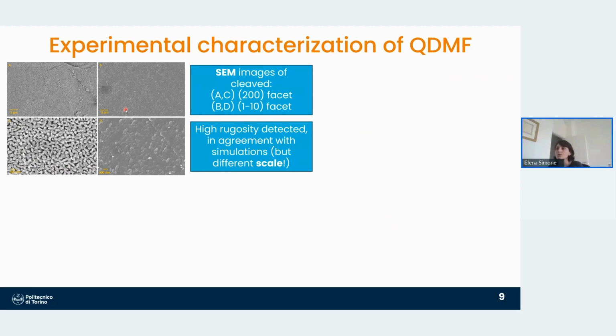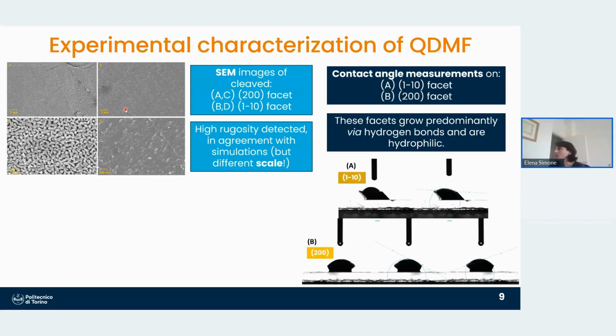So we have to consider that the scales are different between the simulation and the SEM, but at least the differences that we can see were somehow in agreement with the simulation. We also did contact angle measurements, single facet contact angle on the lateral ones, and we saw that they are both hydrophilic, and those are the ones where the hydrogen bonds are present.